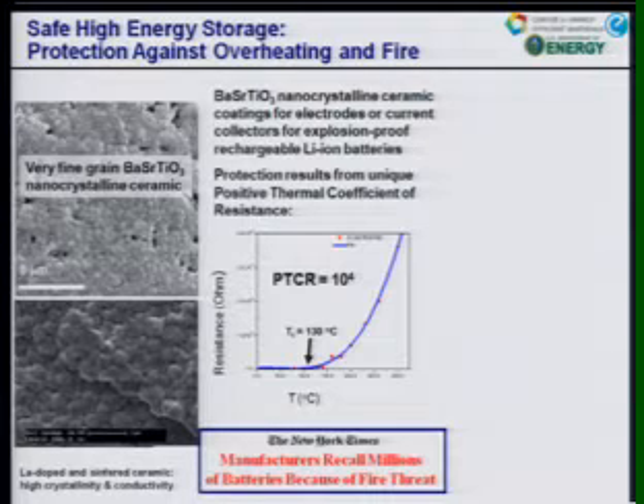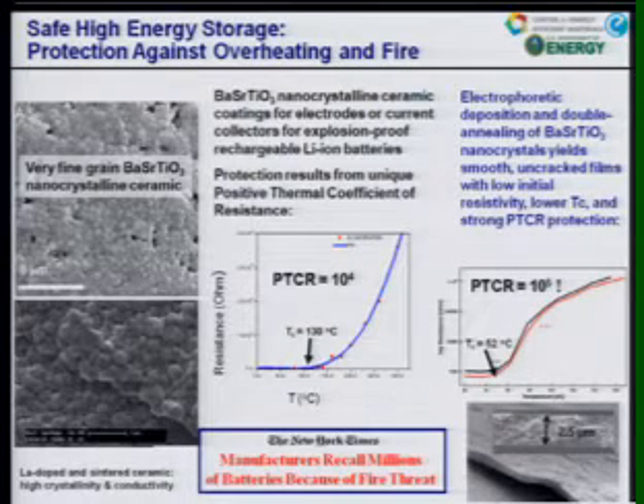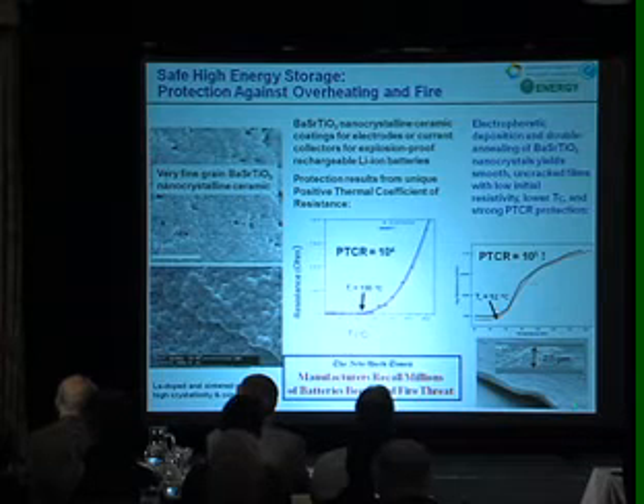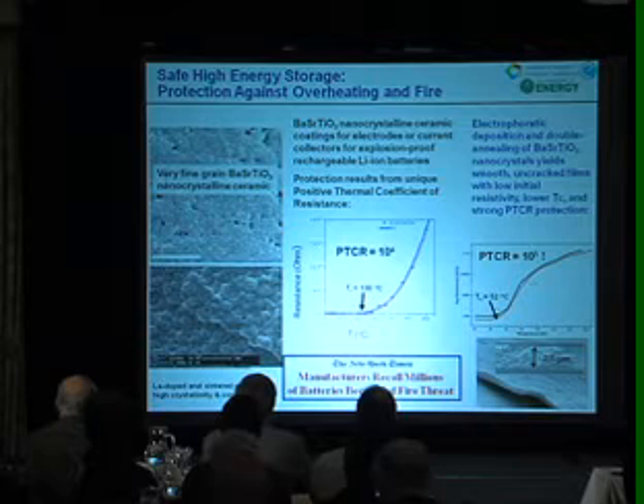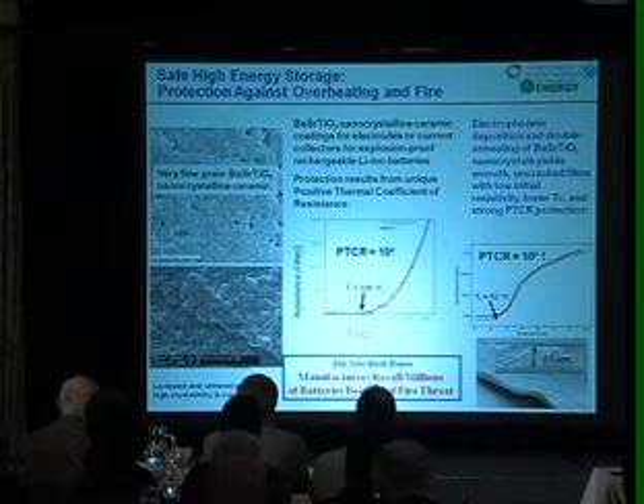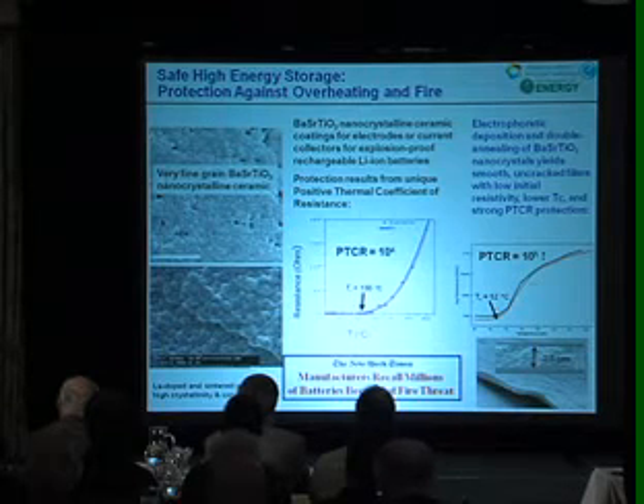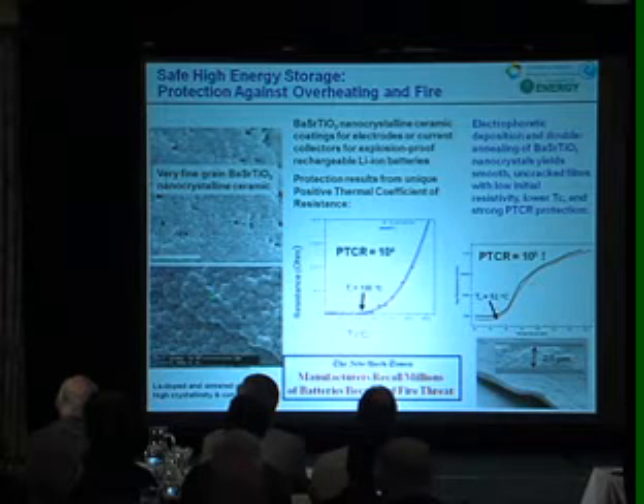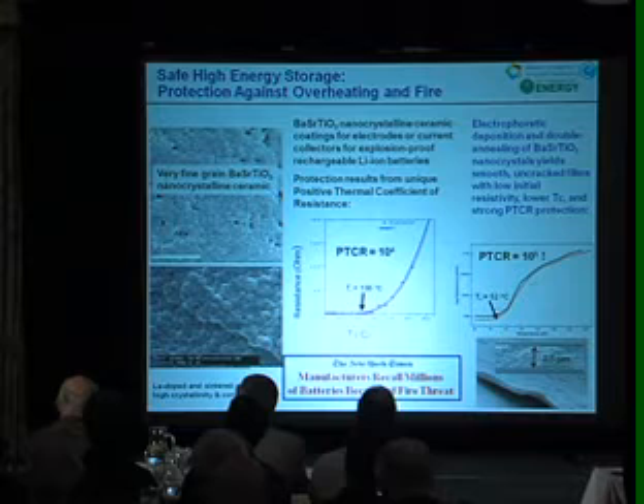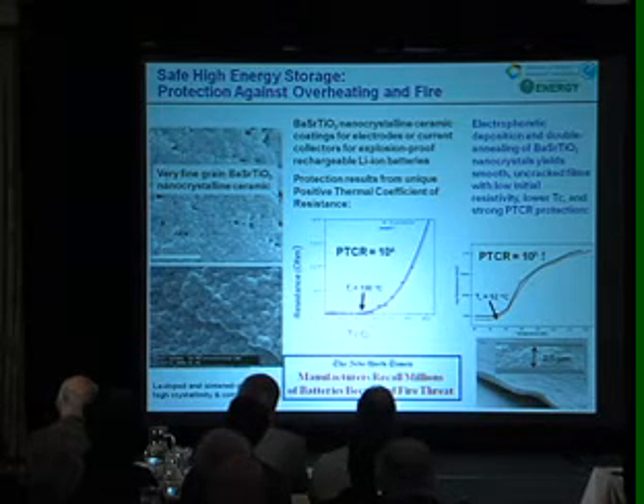And why that's potentially useful, we're all familiar with these news reports of the recall of millions of batteries by most of the lithium-ion battery manufacturers of the world because of the fire and explosion threat. The electrode in the lithium-ion battery is essentially like gasoline. Now, what we have found is that we can make a suspension of this ceramic and use electrophoretic deposition and anneal again to make very, very smooth, thin films of the requisite thinness so that, on the electrode, it's thin enough that it doesn't significantly block the ingress and egress of lithium ions or electrons, but thick enough to have enough grains to provide enough grain boundaries for this positive thermal coefficient of resistivity, this switch effect, to occur.